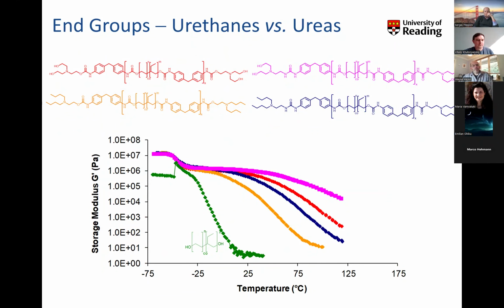Now, I talked about the ability to modify the structures in terms of urethane and urea end groups and look at the effect of simply changing a couple of atoms between comparable polymers. Shown here are the rheological profiles for the urethane and urea derivatives using the ethylene cobutylene mid-block, one of the more apolar systems, to give stronger phase separation. And what you can see is that as we increase the polarity of the end group from a urethane to a urea, you actually extend the duration, thermally, of that rubbery phase.